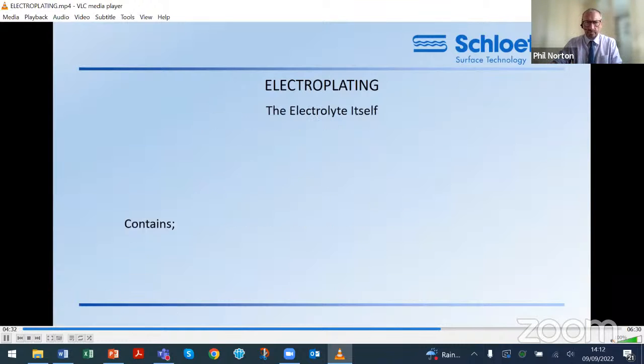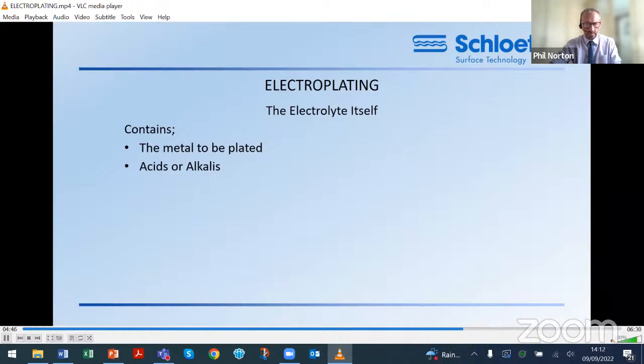The electrolyte itself contains other components as well as the metal to be plated, and all these are there as part of the electrolyte formula, and can include acids, for example sulfuric acid in copper plating, or alkalis such as sodium hydroxide in zinc plating, both of which help to keep the metal in solution. Dissolved solids like salt, which increase the conductivity of the solution.